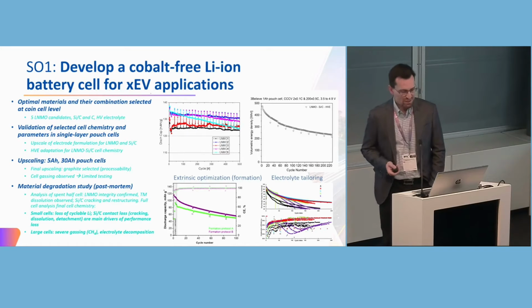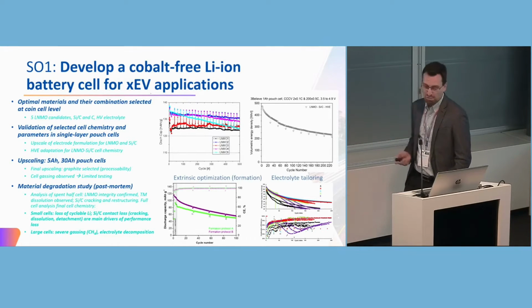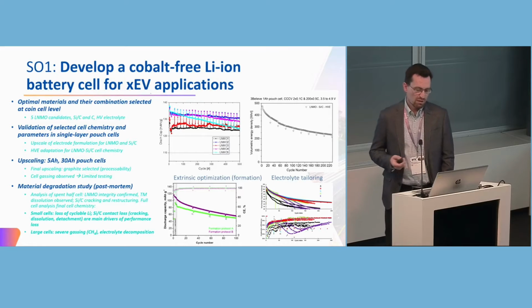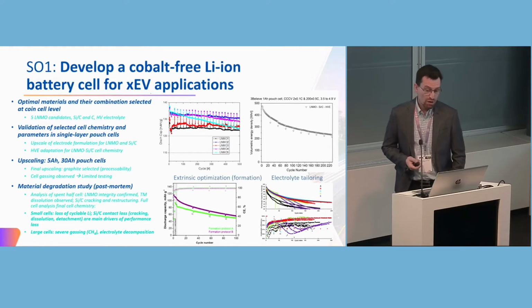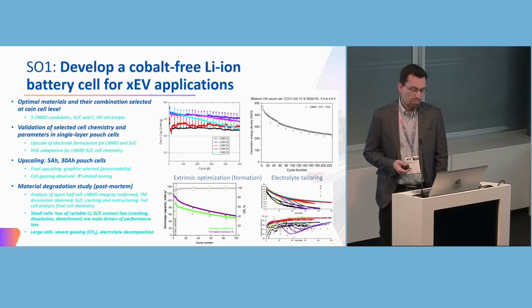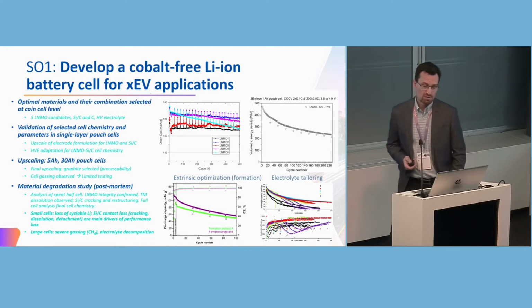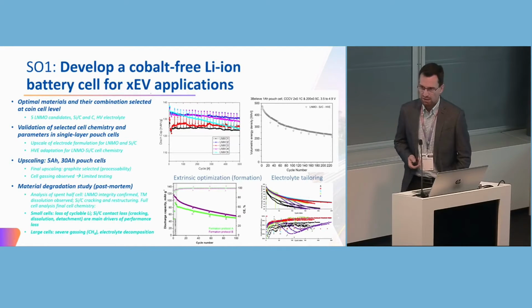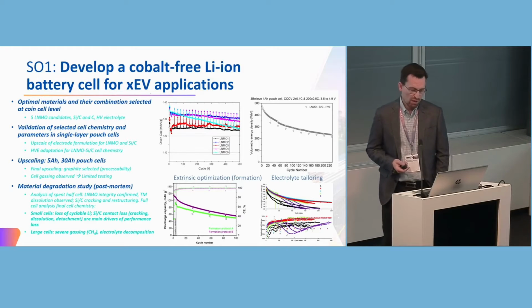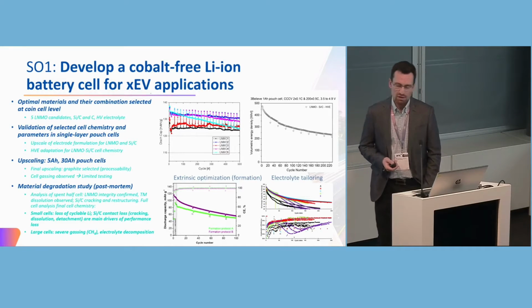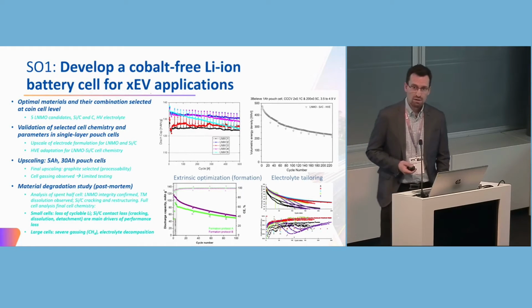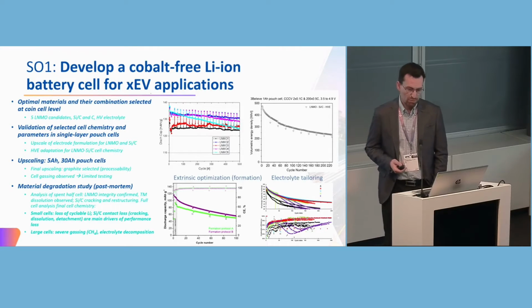However, the difficulties or the challenge begins, of course, when we combine them in a full cell. So here it was possible on initial cycling to achieve 480 watt-hours per liter, so fairly far away from the target. But the key aspect to note here is that there's a rapid capacity fade in this combination of materials. So we have 80% in under 50 cycles. The main driver for this was identified as cyclable lithium loss. So the cyclable lithium is bound up irreversibly.